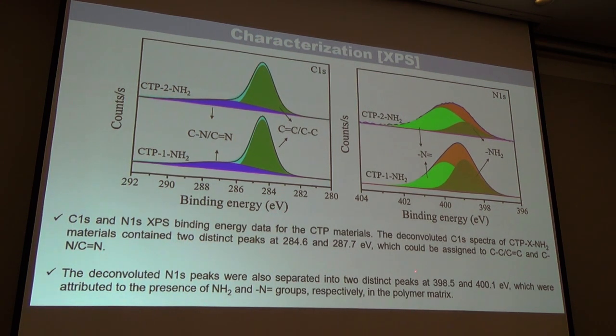The one at 398.5 could be ascribed to the free amine group in the triazine moiety. The one at 400 could be ascribed to the ring nitrogen or the tertiary amine.